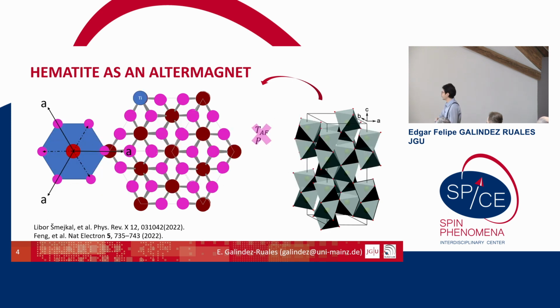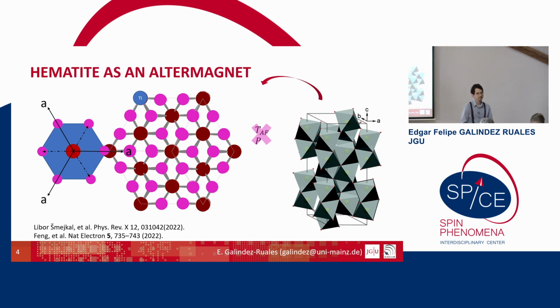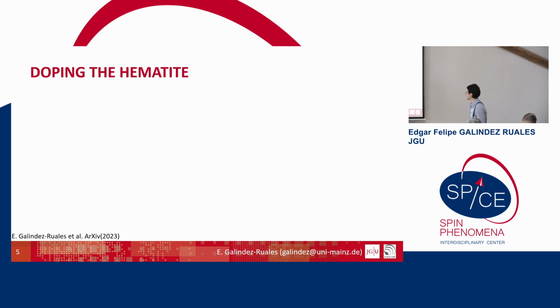So we dope our material with titanium, at 1% of titanium. We grow the sample, or rather people in Israel grow a sample for us, with a stoichiometric target from PLD, and then we have some nice epitaxial thin films that I will try to show you.